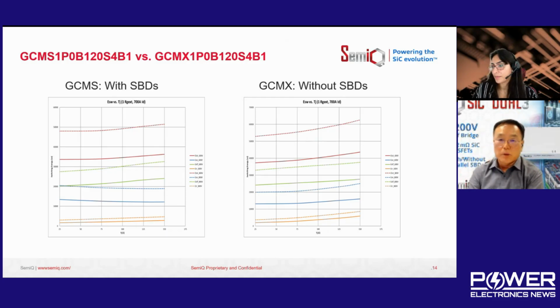Application wise, we look at the industry requirement. The conventional industry is always fighting between efficiency versus cost. That's the reason why they continuously use IGBT modules, because IGBT modules provide reasonable power conversion efficiency at a lower cost. But AI data centers significantly change the power conversion efficiency requirement, because an industrial drive usually runs about 8 to 10 hours per day, but an AI data center runs at full power 24 hours, 365 days. So the conversion efficiency is so important.